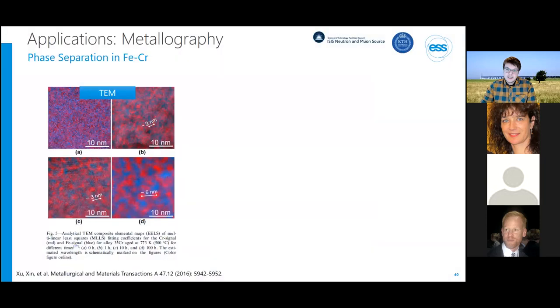In this first example, researchers from the KTH in Stockholm have studied an iron chromium alloy and then systematically exploited the complementarity between different characterization techniques, namely atom probe tomography, transmission electron microscopy, and small angle neutron scattering. Different heat treatments, for example, produce different microstructures with different phase separations in this alloy. And the transmission electron microscopy can show this in great detail, what you see on the slide, but only over very small sample areas. What you see here is chromium in red and iron in blue.